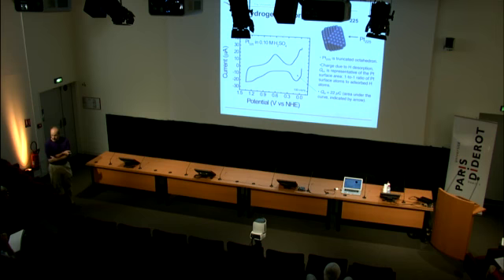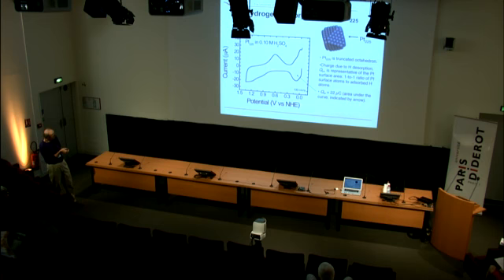So we immobilize platinum dendrimer-encapsulated 225 atom platinum particles on an electrode surface, and then scan out here into the hydrogen region. You can see all the normal things you see for platinum. Here's platinum oxide reduction, and now we see some hydrogen here, adsorption and desorption of hydrogen atoms. From this charge here, the desorption charge, we can measure the total charge due to desorption of hydrogen atoms. And that turns out, in this case, to be 20 microcoulombs.